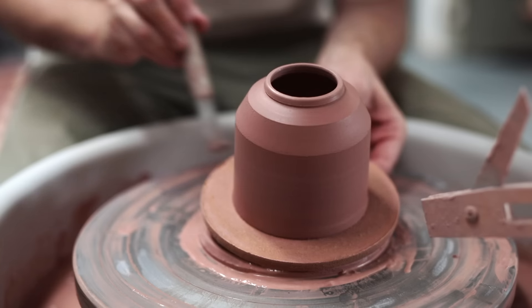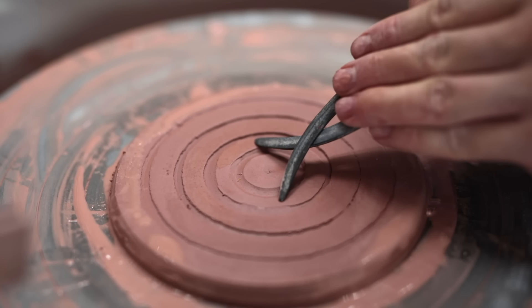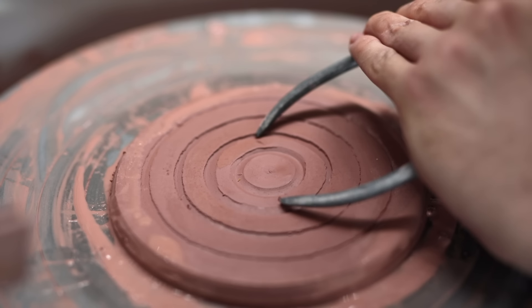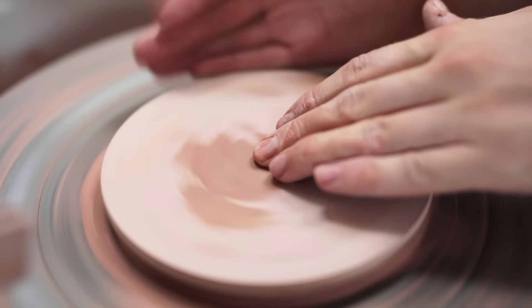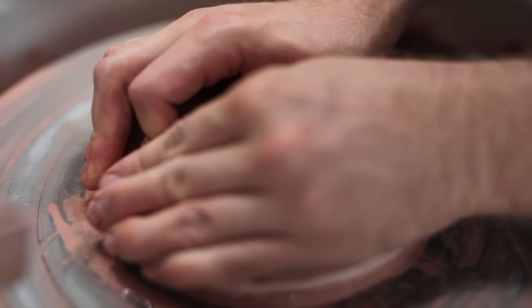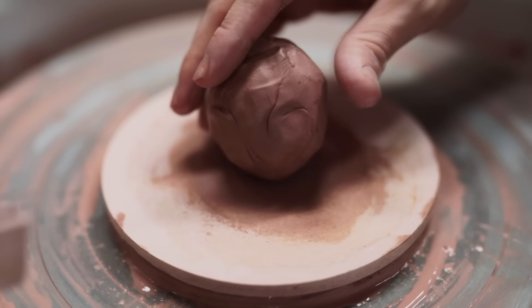It's pretty similar to the original — ultimately it'll be the lid, handle, and spout which do the most work in making them look the same. Next I need to flip my calipers so they measure the same diameter but from the outside — I press the points into the stoneware to make two indentations, then take a measurement of these dots from the outside, giving myself an extra millimetre or two to work with. I prefer having slightly too much material in the lid, which I can turn away for a perfect fit, rather than throwing it the same size and risking warping. Normally you only find out the lid doesn't fit when the components are leather hard, at which point it's very difficult to add extra material — although there is one sneaky thing you can do, which I'll show you later.